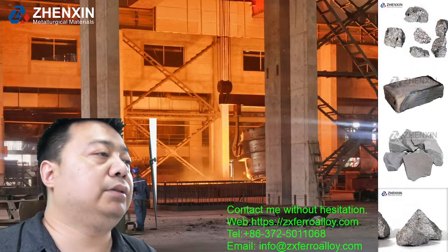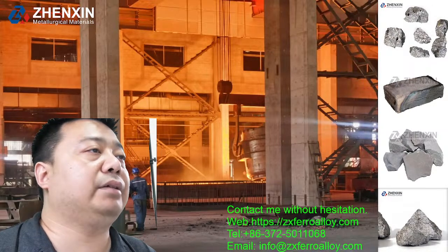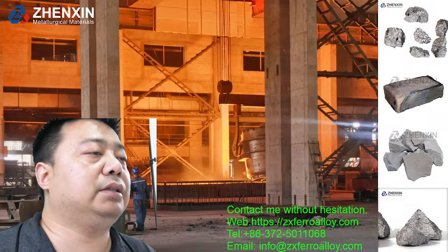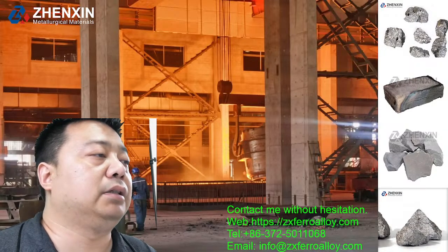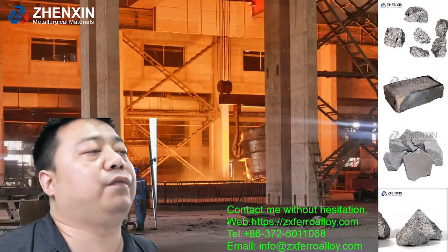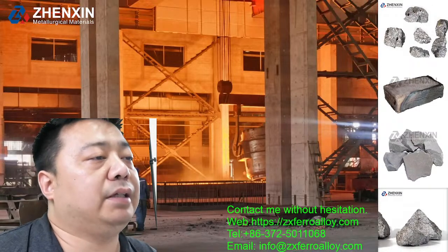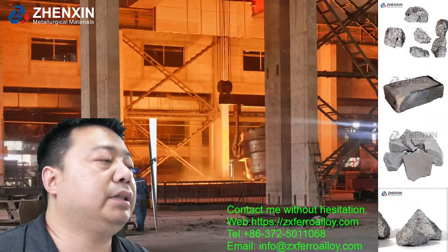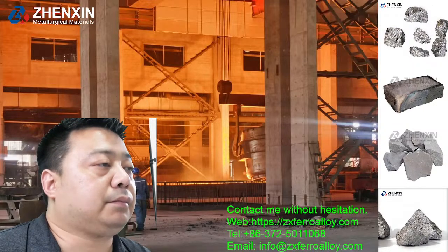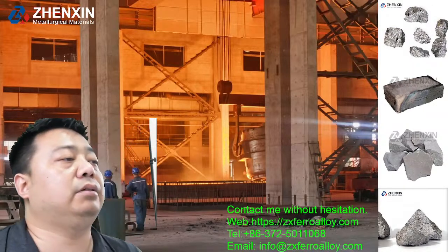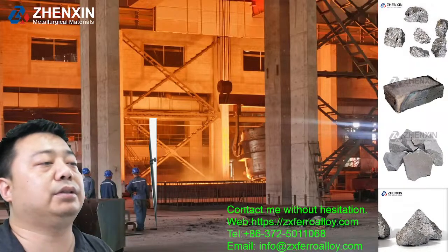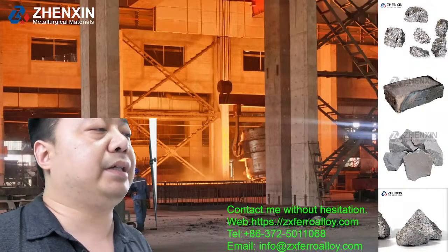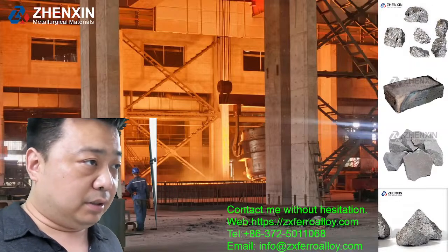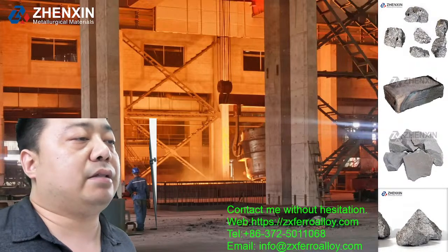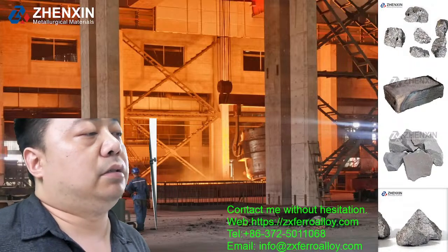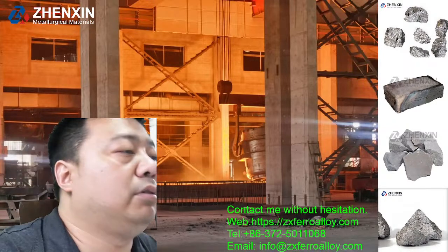As a commonly used deoxidizer in the refining process of molten steel, adding calcium alloy cored wire in the steelmaking process can avoid the formation of long strips of sulfide inclusions, thereby improving the quality of steel. The calcium alloy cored wire is quickly fed into the molten steel with the help of a wire feeding machine to melt in the depths of the molten steel. The use of the calcium alloy cored wire can play the role of deoxidation, desulfurization, and the removal of inclusions.